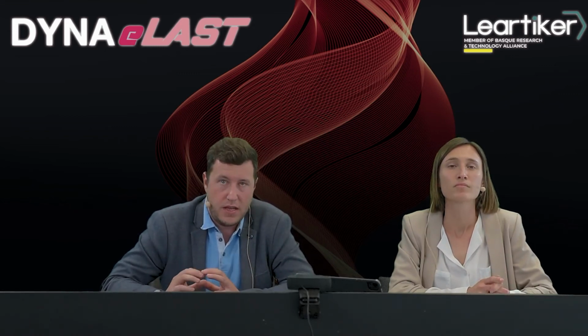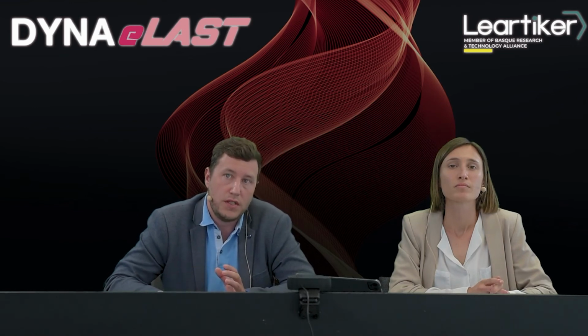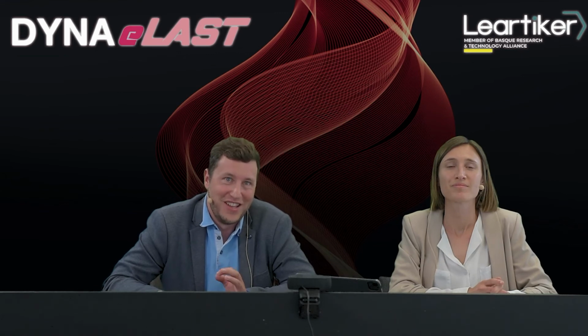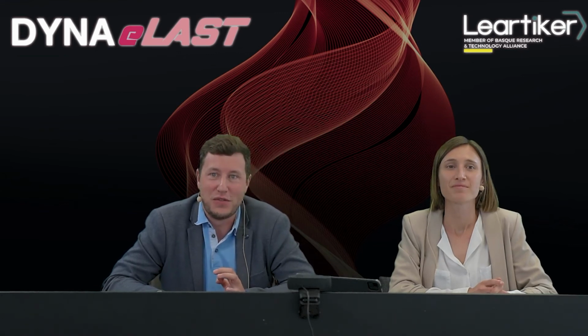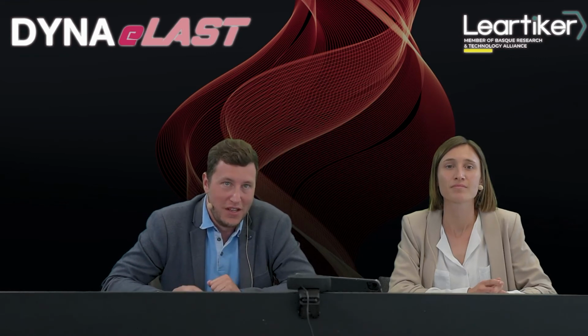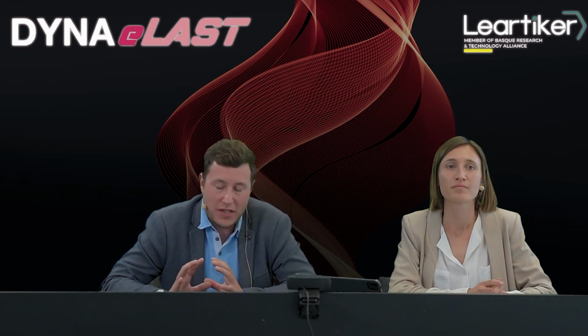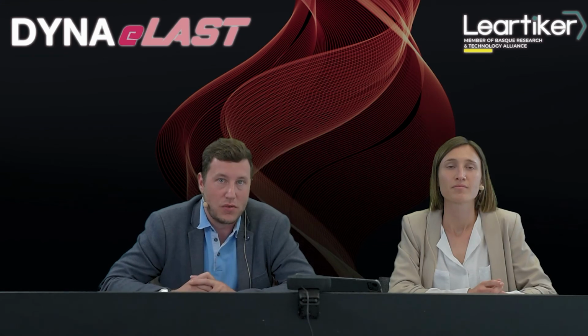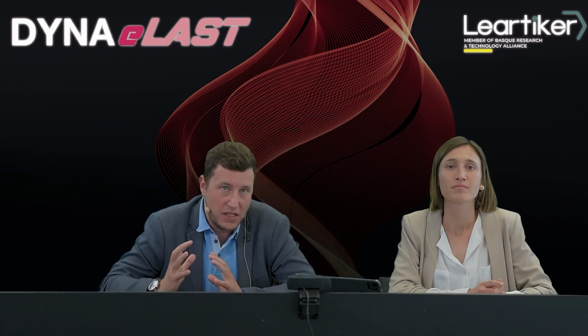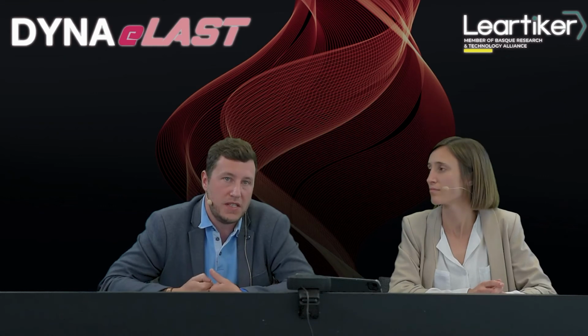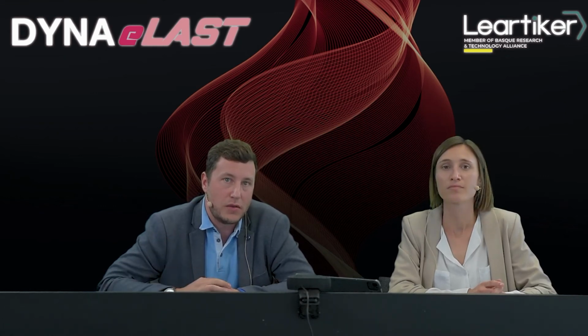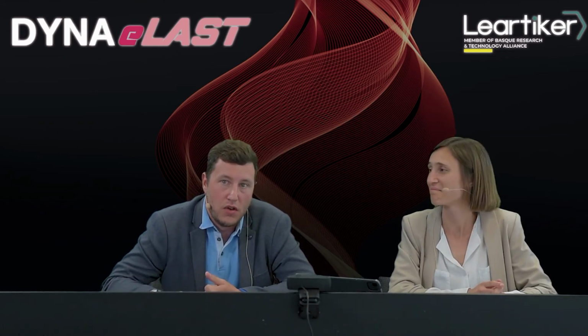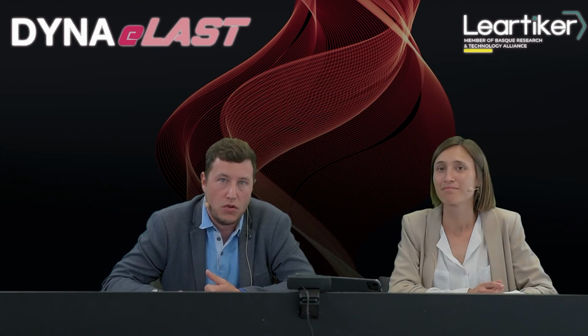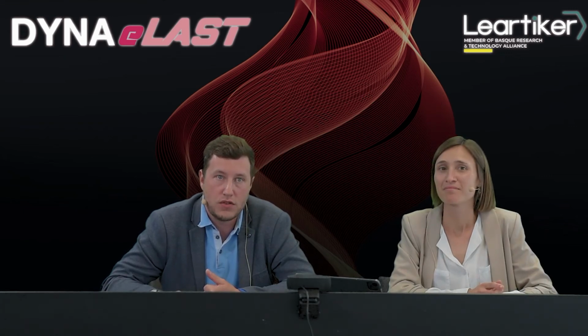The second step is the characterization step. The aim of this step is to get the relationship between the tear energy G and the strain. G is actually fully independent of the crack growth length, and can be characterized before cutting the specimen. The characterization test consists of applying a strain sweep from low strain up to the highest strain amplitude to be applied in a crack growth test.